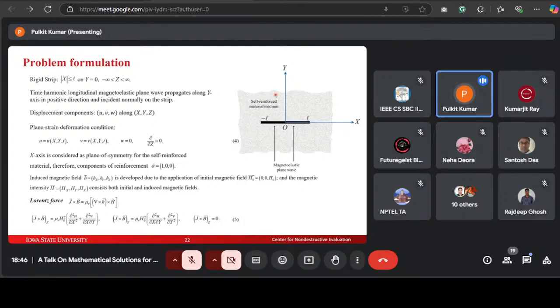An elastodynamic problem for the diffraction of magnetoelastic plane waves, which are incident normally on a rigid strip of finite length 2L positioned in a self-reinforced infinite material medium, is considered. A Cartesian coordinate system OXYZ is defined with mod of x less than or equal to L on y equals 0. A time harmonic longitudinal magnetoelastic plane wave is propagating along the y-axis in the positive direction and is incident normally on the strip. We consider u, v, w as the displacement components in the direction of the X, Y, and Z axes. The deformation conditions are defined by equation number 4. Here, the x-axis is considered as a plane of symmetry for the self-reinforced material.